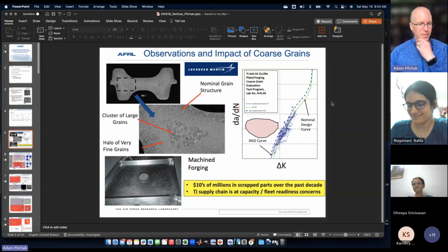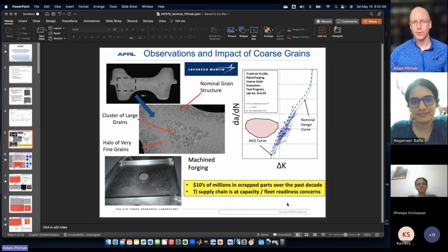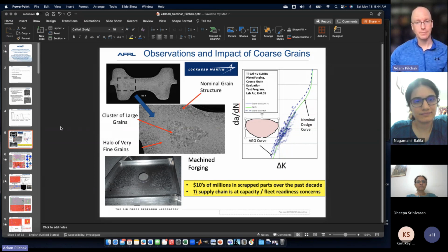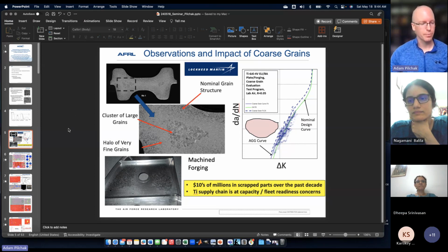Sure. These were classical ASTM compact tension specimens with the direct current potential drop method, but also a traveling microscope to look at the surface crack length. The potential drop measured crack lengths get corrected to match the actual observed optical crack lengths. So that gets you these. What I didn't show here explicitly were any small crack growth measurements. If that's something you're pursuing, there are 2 ways I've done it.